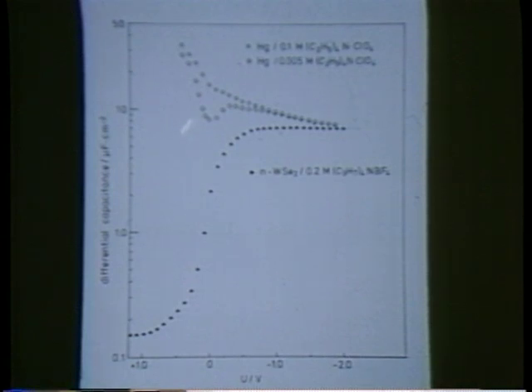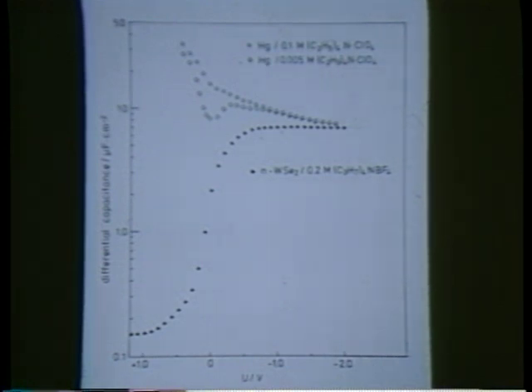And for measurements made by Fawcett, there were the same electrolyte measurements available for mercury. And you see, that is a zero point of charge for mercury, and just to the same scale. But the capacity in the very negative range, where we have a high concentration of electrons on the surface, comes very close to the value of mercury, and it shows clearly that now we have practically a metallic behavior.